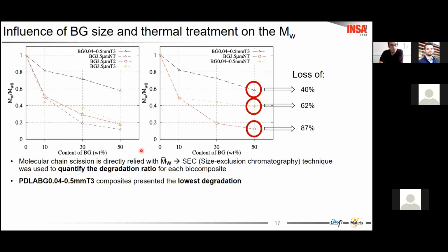So this size exclusion chromatography study was performed to obtain the molecular weight value for each sample. As the chain scission is directly related to the molecular weight, this technique allows us to quantify the degradation of each sample.